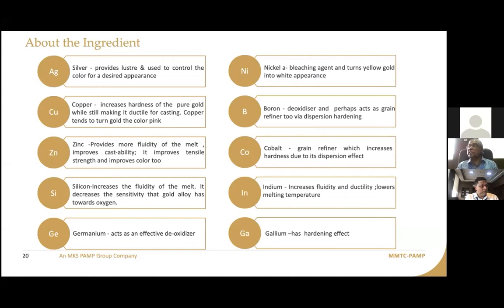So silicon and zinc need to be balanced. While they have all these benefits, they also have detrimental effects. If your silicon increases too much, it will cause cracking. So you need to be balanced. You cannot just add it, and it has very limited solubility in gold and silver. It is soluble in copper. So when you are talking of silicon, you have to be very particular about the copper to silicon ratio you are maintaining, because the silicon needs to be soluble. Otherwise, it will form a segregation and lead to cracking of your jewelry.